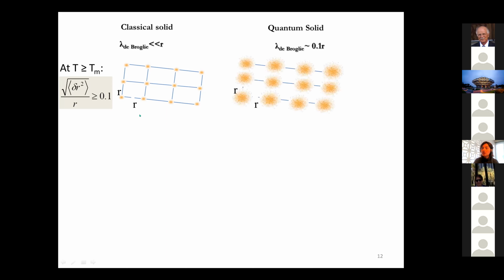Now, let's look at the other case, what do we mean by quantum solids. Quantum solids are obviously solids where the de Broglie wavelength gets close to the interatomic distances, and basically the translational symmetry is going to break to avoid the overlap of these hard cores. There's a similarity here. There, the amplitude of the thermal vibration gets close to interatomic distances, and you get instability in the lattice, or melting. Here, similarly, if the delocalization, the quantum zero-point motion disorder, is sufficient compared to the interatomic distances, you get the same effect, but it's not thermodynamic melting, it's quantum melting. And it's basically coming from the uncertainty principle.